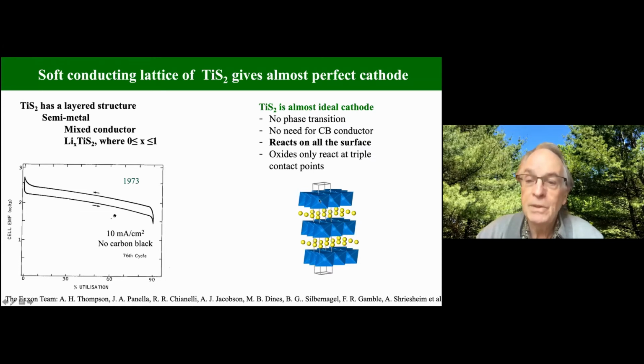Jeff has already mentioned these are layered structures, and there's a tendency for the transition metals to go into the lithium layers. This has some good and bad consequences. Obviously it reduces the diffusion of the lithium, but in the case of titanium disulfide, we intentionally, in the commercial product, put about 0.5 to 1% titanium in this layer. This, in fact, reduced the corrosion of the material substantially. Now, I list at the bottom all my colleagues that made this possible.